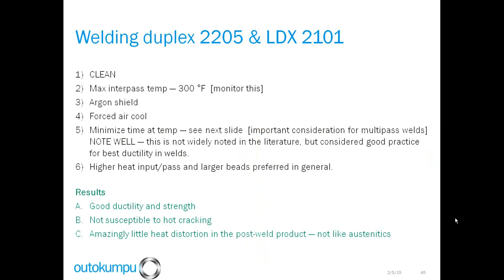Welding of the 2205 and the 2101, as Gary said, it wants to be clean. You can avoid pitting, you can avoid little inconsistencies in the weld by just enforcing that your welders are cleaning the material well. The interpass temperature, 300 degrees F or 150 degrees centigrade. You need to monitor this. The guides all say that you do not want to spend a lot of time going through the transition. You need a quick cool. You also need to get down to this interpass temperature.